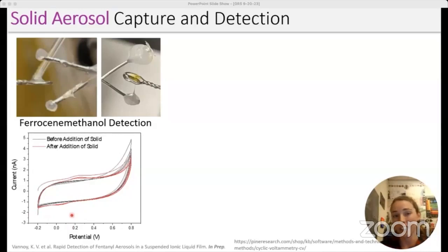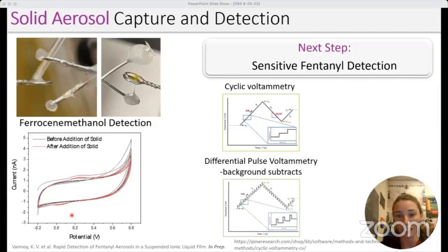So our current experiments right now are applying this method towards fentanyl detection. One of the first shifts we made when going into fentanyl detection was we swapped cyclic voltammetry for differential pulse voltammetry. Cyclic voltammetry is what I've shown you throughout this whole presentation. It's just a very simple ramp of potential, and it makes this triangular waveform. Differential pulse voltammetry is the same ramp, but there are some small potential steps along the ramp, and that's just allowing us to subtract out some non-Faradaic current. Basically, it's just a background subtracted cyclic voltammetry. That's giving us a little bit of extra sensitivity.